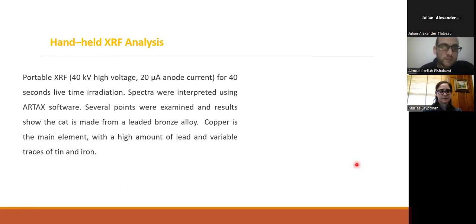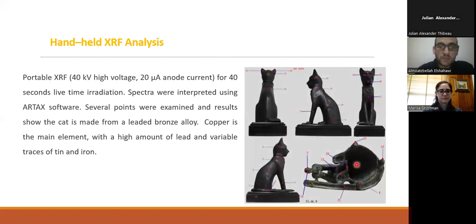As for the handheld XRF analysis, the cat has also been analyzed using handheld XRF to learn more about the elemental composition of the cat alloy. The results gave us information about the alloy of the cat: it is made from a leaded bronze alloy. Copper is the main element, with a high amount of lead and variable traces of tin and iron. As we can see here, the XRF spots.